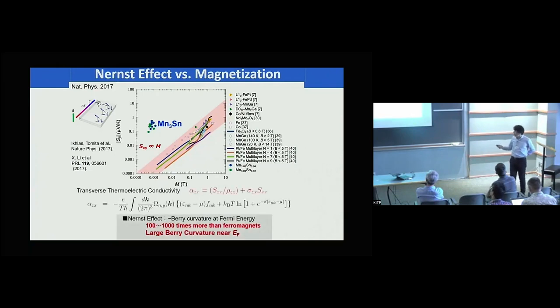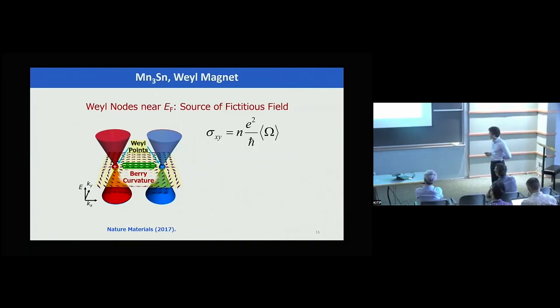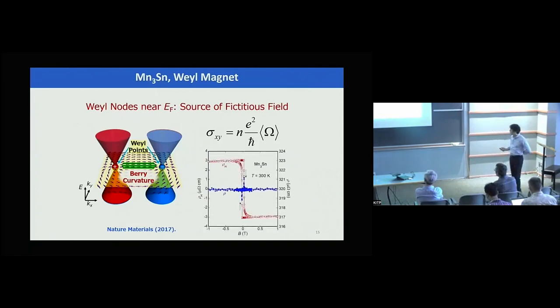This actually tells you that there is a large Berry curvature near the Fermi energy, because it's automatically telling that the thermoelectric conductivity is so large. So this means there has to be a source and drain of Berry curvature, which is a Weyl point near the Fermi energy. Another interesting point is that despite the fact that it only carries such a milli-μB moment, one can control the magnetization so easily, with as little as 100 Gauss. So magnetization somehow picks up a small field and then the whole resistivity flips.